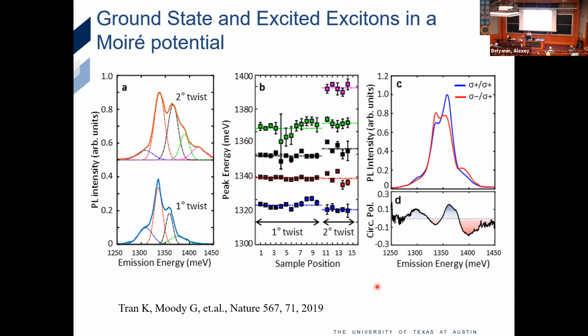So ideally, you want better spatial resolution so you can probe an individual Moiré supercell. Right now, we're using a micron beam, so we're actually probing hundreds or a thousand Moiré supercells at the same time, right? So we don't know what spatial inhomogeneities are present. For example, this peak is kind of broad, but why is it so broad? Perhaps just because of small variations in the Moiré cell.